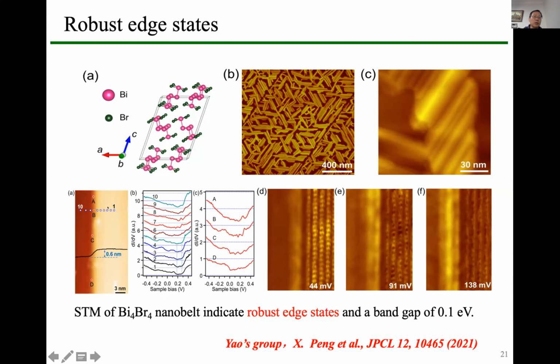We use STM to measure the dI/dV spectra, which corresponds to the local density of states. If the tip is far away from the edge, then we can find that there is a gap here. The gap is about 0.1 eV. But if the tip is close to the edge, then we can find some states in the gap. These states are attributed to the edge state.